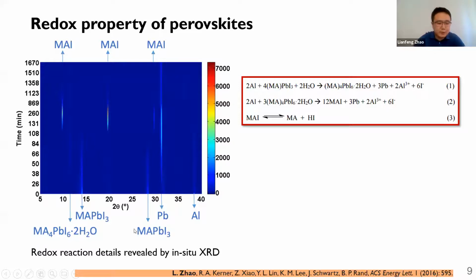We did an in situ XRD measurement, which gives us more details about the chemical reactions. This bright peak actually corresponds to metallic lead. So this data gives us more details. It is the redox reactions between the lead ions in perovskite and the aluminum electrodes that induced the degradation.